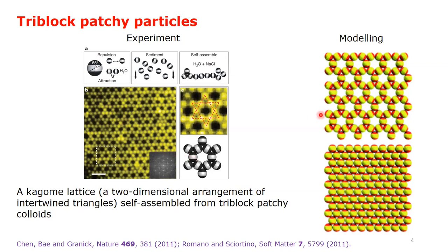This seminal work provided motivation for a number of computational studies. For example, Romano and Sciortino captured the self-assembly of the Kagome lattice from tri-block patchy particles at low temperatures and pressures, and predicted the formation of close-packed hexagonal lattice at higher pressures.